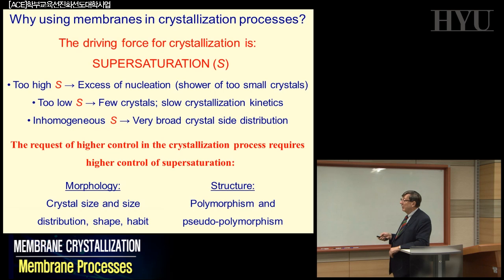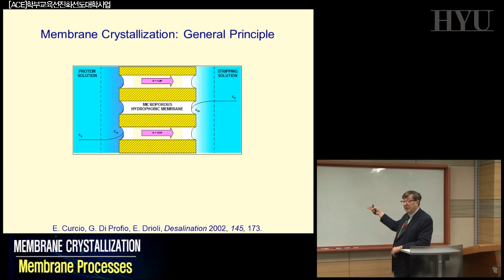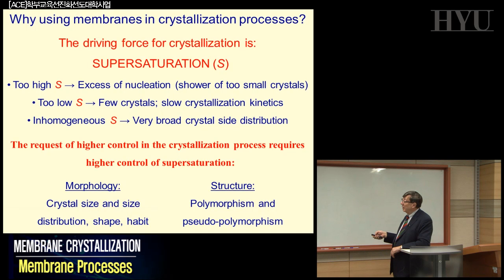You can also very often have a supersaturation which is non-homogeneous. We saw, for example, that when you cool down, it's easy to have non-homogeneous supersaturation. And in this case, just the opposite of the low case, you have a very broad crystal size distribution, and not equal. Particularly in some applications, such as drugs or catalysis, you want to have all the crystals as similar to one another as possible, and you decide which one is right. So if you want to improve the performance of your crystallization, basically you have to find a way to have very good control of the supersaturation step. That is the point on which you have to operate.